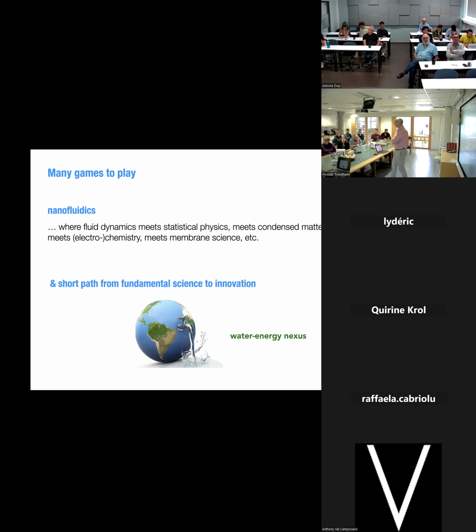One of the systems you mentioned relatively early struck me. I think you said that for the dielectric constant, there is an anomalous behavior. And of course, geometry is a parameter when we speak about nanofluidic systems. So my question is, did you try to find scaling laws? We tried water at the surface, and the surface tension of water, when you shrink the system very low, is still regular. It's inverse to the radius, the size of the system.